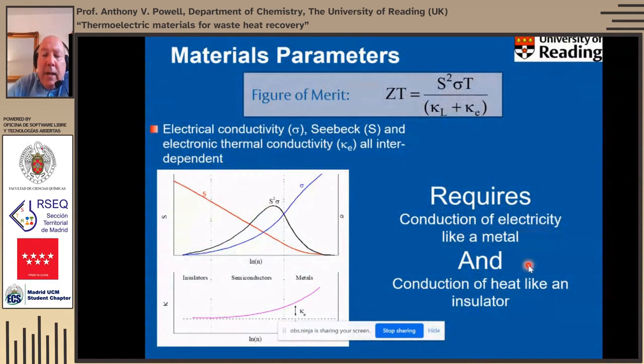And it depends on the fundamental materials parameters, the Seebeck coefficient, the electrical conductivity, and then the thermal conductivity, which has got two components to it. It's got that due to the charge carriers, the kappa E as it's indicated here, and it's got a component due to the vibrational modes of the solid, the phonon component, which I've labeled here as kappa L, kappa lattice, for the thermal conductivity due to the phonon transport.